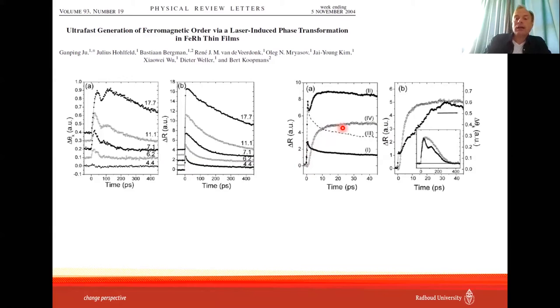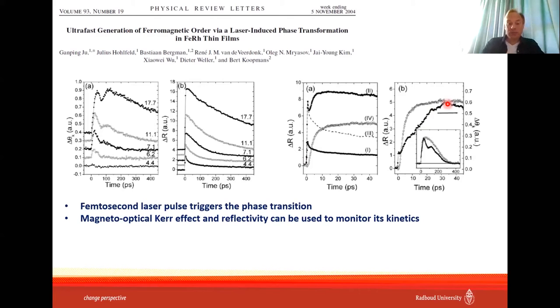And next to this, there is also a very slow increase of something, and this very slow increase is an increase of the contribution from the lattice in the reflectivity. So this is what we assign to lattice expansion. And if you put together the rotation, shown with black dots, and the reflectivity, which corresponds to the lattice expansion, you can see first that the Kerr rotation has a very fast jump, so something appears very fast, much faster than the structural transition. Then the structure expands, and then magnetism follows more or less the lattice expansion, but already on a longer time scale. So basically, from here we can conclude that first, the femtosecond laser pulse triggers the phase transition. This is good news.